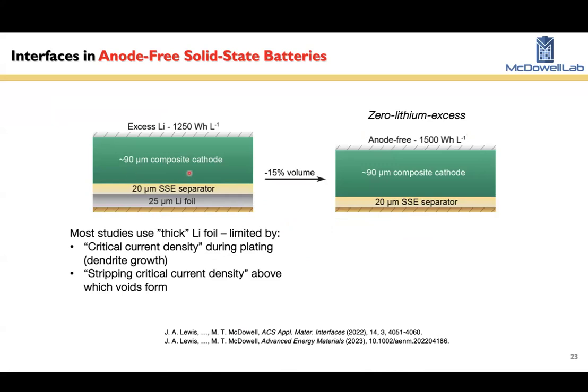So normally, well, in many testing scenarios, what you see in the literature is that a battery will be constructed with a cathode, like an NMC type cathode, some sort of separator that's usually much thicker than 20 microns, and then a lithium foil. And usually the foils are really quite thick, that people test at lab scale, on the order of hundreds of microns. But for a commercialization setting, you'd expect thicknesses on the order of this left image here, where you have a 25 micron or so thick lithium foil, and these other thicknesses are associated with what you can expect to get this energy density with. So this is a normal excess lithium cell, we call it.